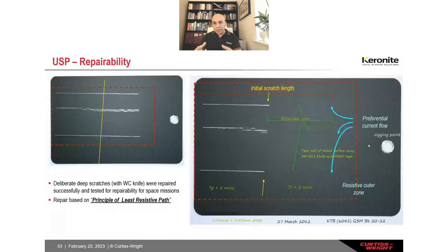And finally, another strong point is the repairability. This job was done for one of the space missions. What we did here is we coated a plate. We scratched these 3 long scratches with a diamond tool, and we masked 50% on the left with a tape and a paint, and then we recoated those damages.